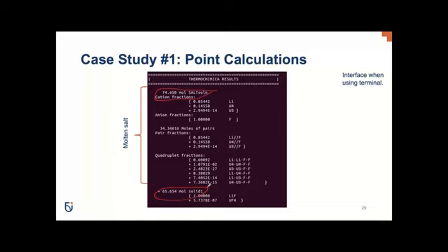The output here that is given in this large block is model class specific. So depending on what kind of thermodynamic model you're using, you get a bit of a different output. So in this particular case, what's a little bit more unique to the modified quasi-chemical model, which is what this is, it provides as output the quadruplet fractions, which are shown here.